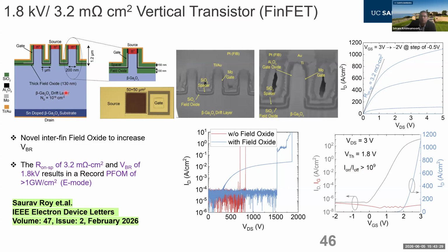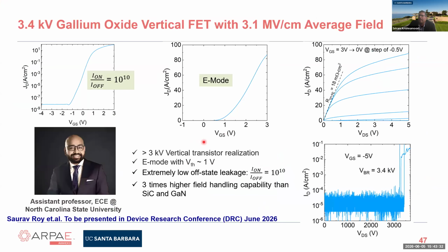And even more recently, this is some very new data. It will be presented later this month at the Device Research Conference. Again, Sriram went on to become a professor at NC State. So Sriram is going to present this at DRC at the end of this month. So we've been able to make 3.4 kilovolt transistors. Again, excellent on-off ratio, 10 to the 10. These are enhancement mode. Slightly higher on-resistance in this case, and we know how to make this better in future generations. And we see very low reverse leakage for the transistor until it catastrophically breaks down at 3.4 kilovolt here.